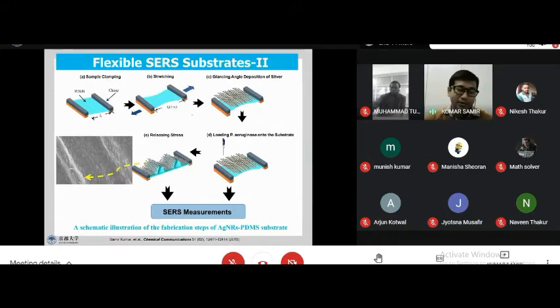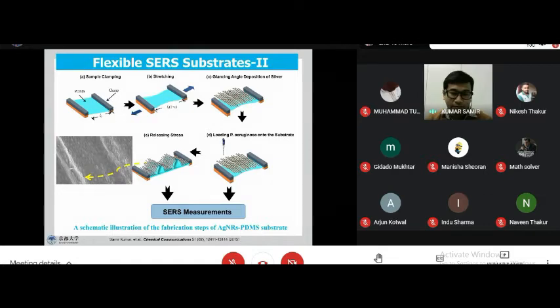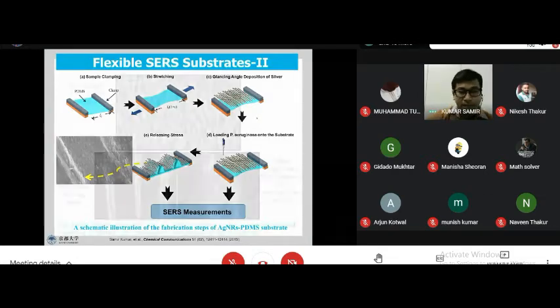So we know how much stretching is required to make these wrinkles. After that we deposited silver nanorods, and then we put bacteria on top of it, did the measurement, and then we released the strain and again did the measurement. On releasing the strain, these kinds of wrinkles are formed because of the difference in the Young's modulus between the silver layer and the PDMS layer.